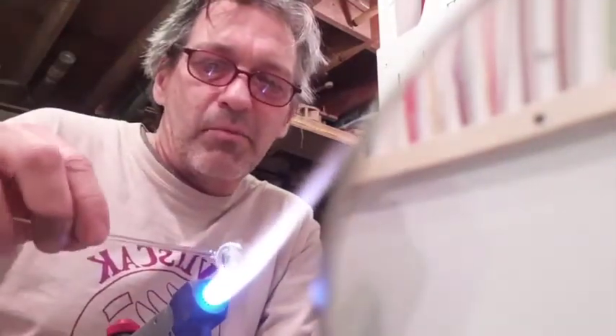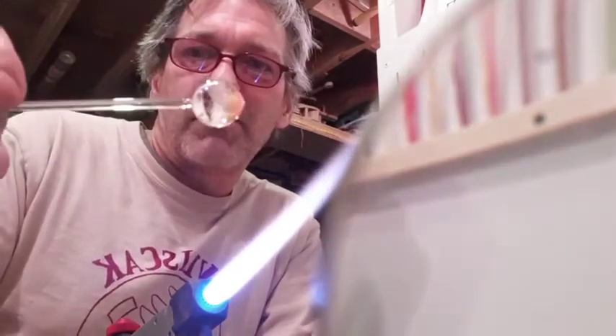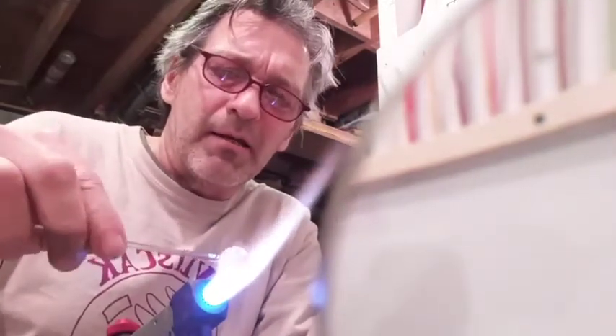Now I'm going to heat it, let that last little nub of imperfection pull in a little bit, let it rest, adjust on its own. You can heat it strongly, but heat it too strongly, it's going to start oxidizing the surface. So it needs a little bit of help. So I'm going to go just a little in my marble mold. And we improved the sphere.